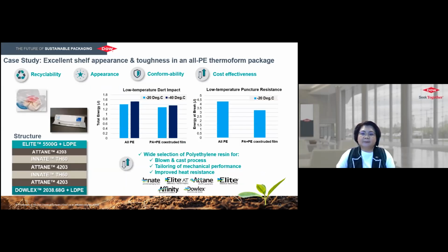The low temperature dart impact and puncture resistance charts at negative 20 and negative 40 clearly show that all PE-based film demonstrates better performance than the PA-PE co-extruded base film. Such all PE-based film is targeted for low to no oxygen barrier requirement, low and room temperature conditions, such as frozen food and medical device packaging respectively. So depending on the demand in performance from brand owners or end users, Dow has a wide selection of polyethylene resins for different fabrication processes, as well as providing tailored solutions to meet packaging expectations.